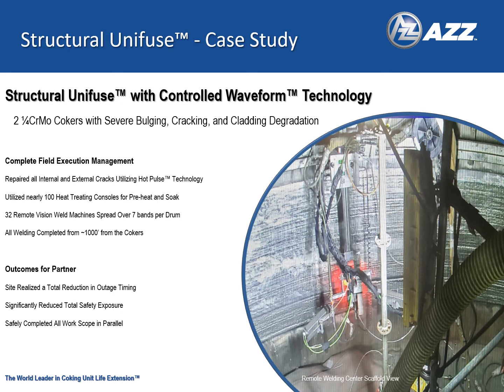Prior to the installation of the overlay, all internal and external existing cracking was repaired using the AZZ hot pulse high-speed TIG welding process. Nearly 100 heat-treating consoles were needed to support this project for preheat and post-weld soak. A total of 32 remote vision welding systems were used. All welding was controlled from 1,000 feet away from the vessels. The project met their schedule and safety requirements and allowed work to be performed in both vessels in parallel.